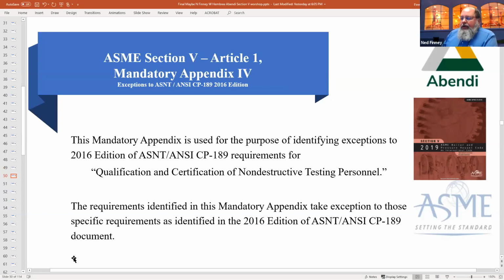We'll talk more about Mandatory Appendix 3 later. Mandatory Appendix 4 is the use of CP-189, qualification and certification of nondestructive examination personnel. It is a standard. It's not a recommended practice. So there's a difference in how it's used. There's a lot fewer exceptions. Requirements identified in this mandatory appendix take exception to those specific requirements identified in the 2016 edition of CP-189. So we added some additional requirements, but not nearly as many as we did for TC-1A because of the difference between a standard and a recommended practice.